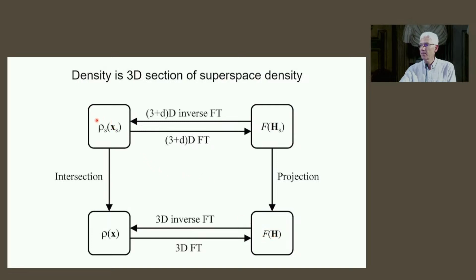And in superspace, we have a 4-dimensional generalized electron density, and we can do a Fourier transform, and we get also the structure vectors. And those are the same structure vectors as here. We have a projection of 4 indices in 4-dimensional space to 4 indices in physical space. And the big thing which Janssen, Janner and de Wolff succeeded in is doing the inverse of this projection operator, which in general should not be possible, but because we can do this indexing of Bragg reflections, we can do the inverse projection. And in superspace, it's this generalized density, and we take an intersection as physical space to get the electron density, which we really want.